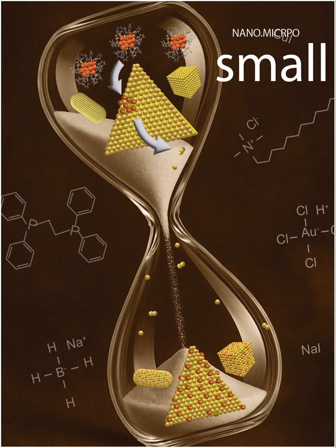Okay, now this whole mechanism sounds a bit weird. You said copper is generally less noble than gold, so gold usually doesn't like to react or be displaced. How does this anti-galvanic thing work where copper seems to be kicking gold out? Yeah, this is probably the most scientifically intriguing part. It is counterintuitive based on bulk chemistry. They actually observed gold ions, specifically [Au2(DPPE)2]2+, leaching out into the solution during the reaction. Gold leaving the nanoparticle, while copper goes in. Exactly. Unexpected, right?